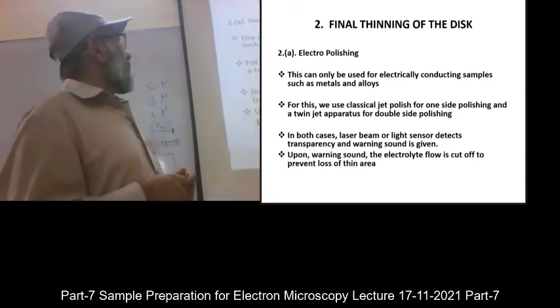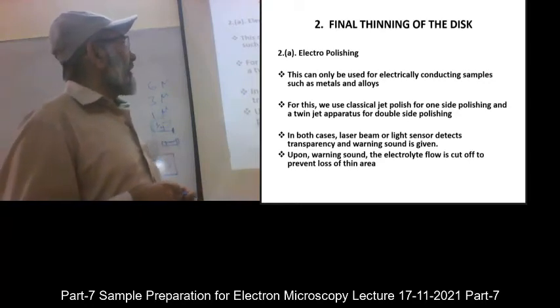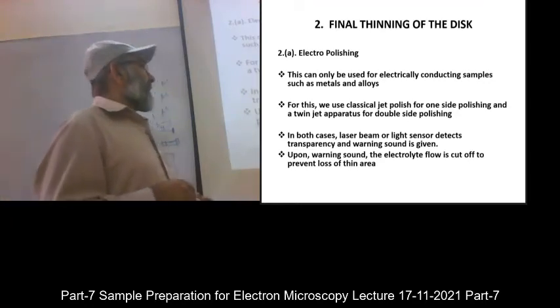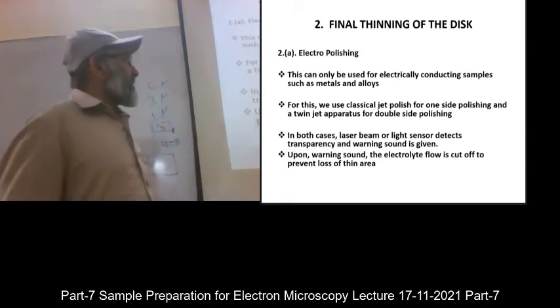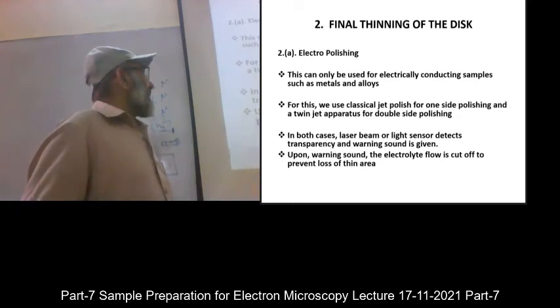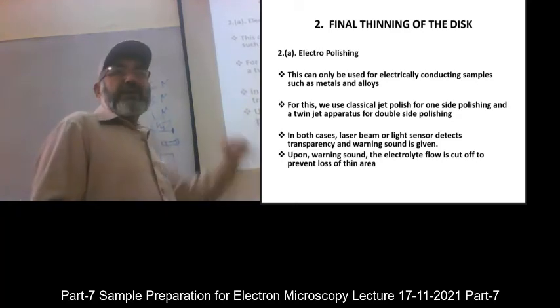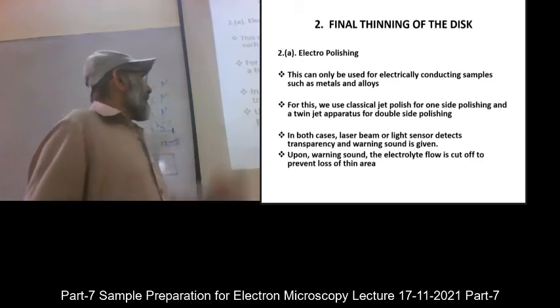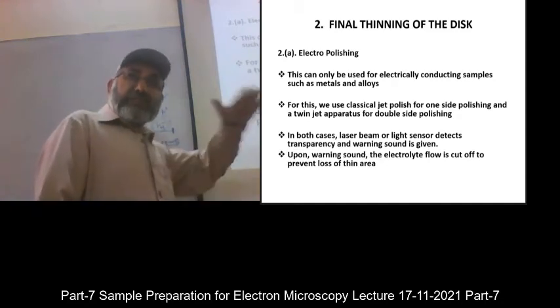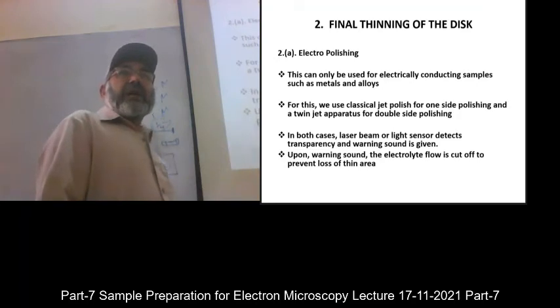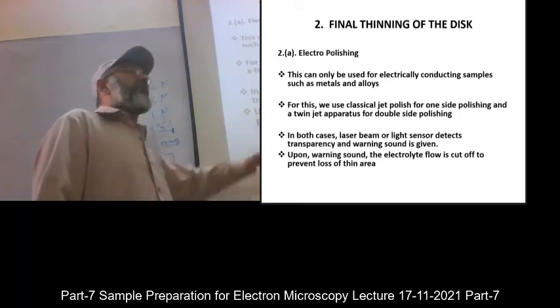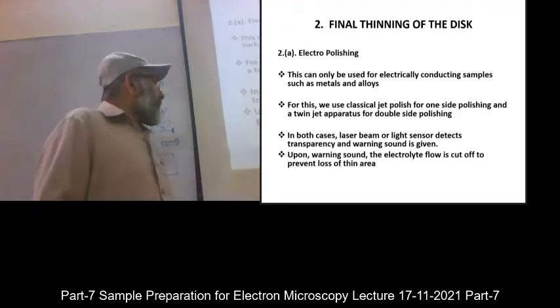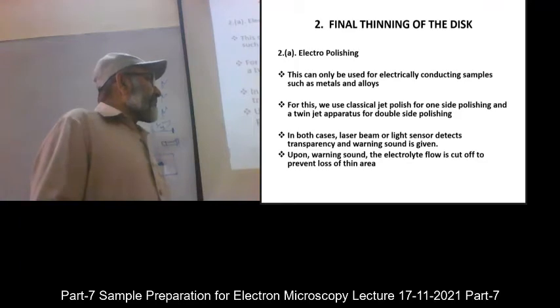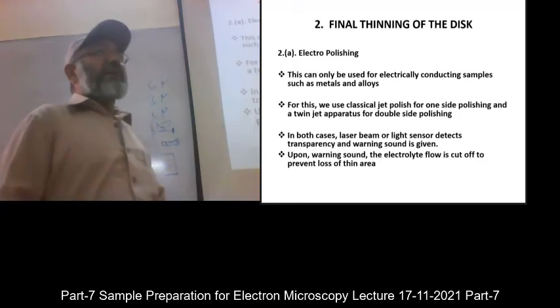Final thinning of the disc, electro polishing. This can only be used for electrically conducting samples such as metals and alloys. For this we use classical jet polish for one side polishing and a twin jet polish apparatus for two side, double side polishing. In both cases, laser beam or light sensor detects transparency and a warning sound is given. So when it reaches a specific thickness, a beep or a warning sign appears and it tells you not to go further in that area. Upon warning sound, the electrolyte flow is cut off to prevent loss of the thin area.